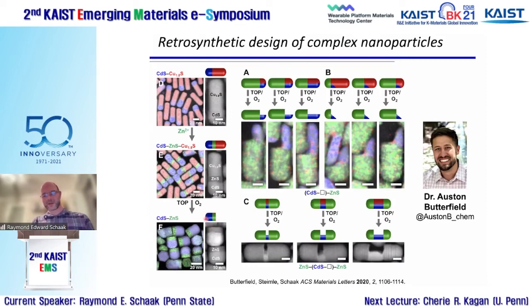From a nanoparticle perspective, these are Janus nanoparticles, but one side, this is cadmium sulfide, zinc sulfide, one side having a faceted tip, the other having a flat tip. So that level of control, both compositional asymmetry as well as faceting asymmetry.